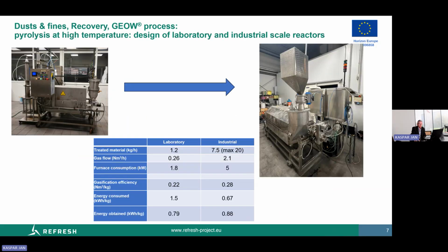If I show you, the reactor is quite small. This is a reactor which is capable of treating up to 20 kilograms per hour of material. These reactors can be made modular, and so we, for example, are working on a parallel project where 10 of these reactors are used in parallel and can process tons and tons of materials per day. And essentially, what is important in all the discussion is that we have at this point a gasification efficiency which is about 0.2 to 0.3 cubic meters per kilogram of material.